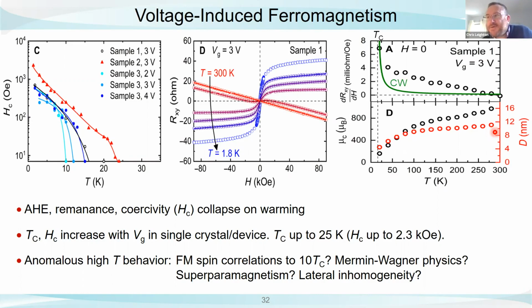Yeah, well, it's a good question. I should say from our experience, what the word damage actually means, first of all. We certainly see what you could call damage at positive voltages in particular. Because the voltages I showed you here, we go through to about 3 or 4 volts. We make a lot of oxygen vacancies. If you keep going, you will exceed the electrochemical stability window of the ion gel, the ionic liquid. Bad things happen. We can also sometimes etch materials, right? We can literally get to the point where a positive bias, I think we have just so many H+ ions around that we're essentially acid etching the material. And maybe that's what the person who's asking this question is asking about.